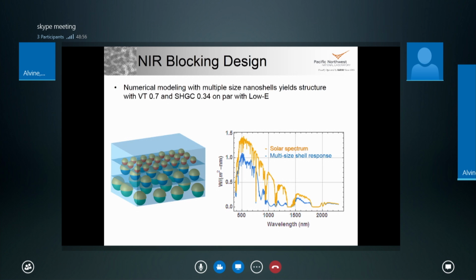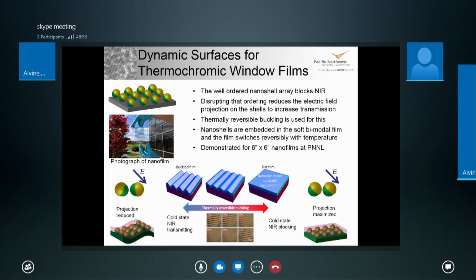The other thing these spectrally selective systems can do, as I mentioned, is allow for dynamics. Because the optical response of these is dependent entirely on the geometry and orientation of the nanoshells, when you disorient the film, or essentially randomly orient the particles, then the projection of the incident light's electric field on the particles reduces.